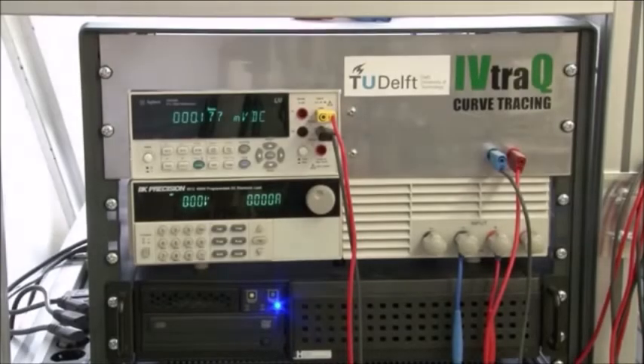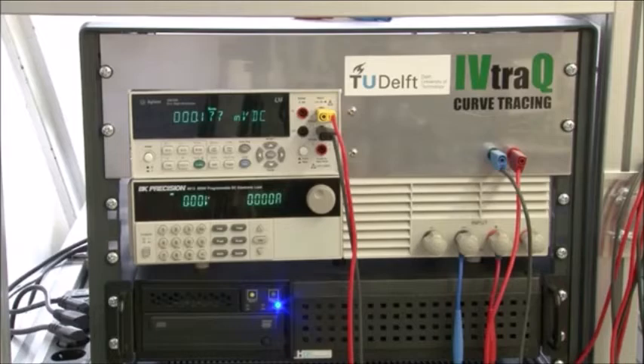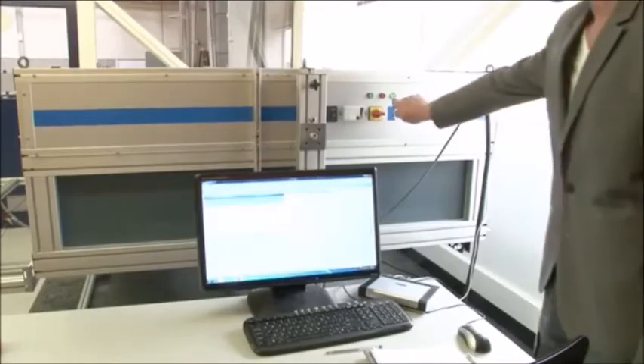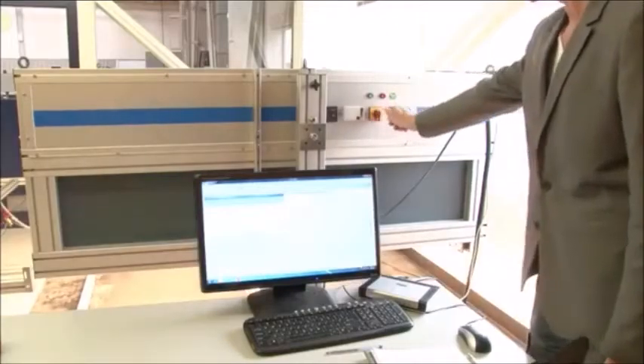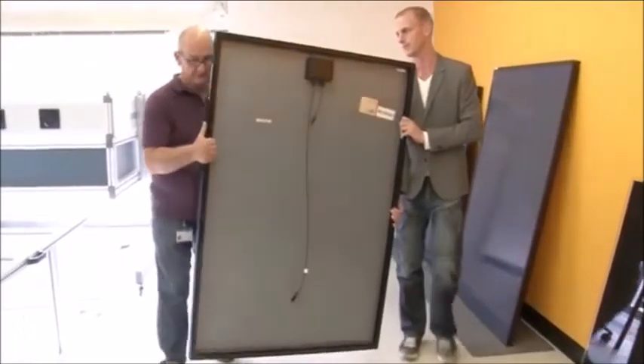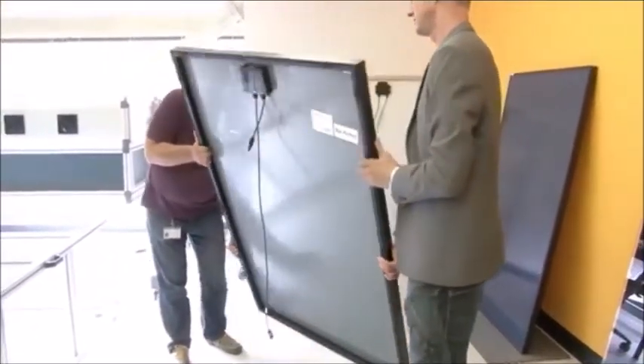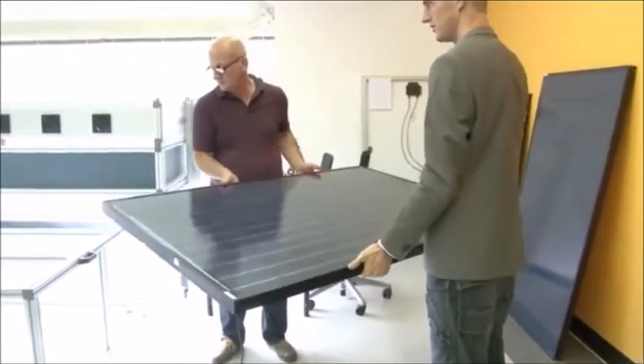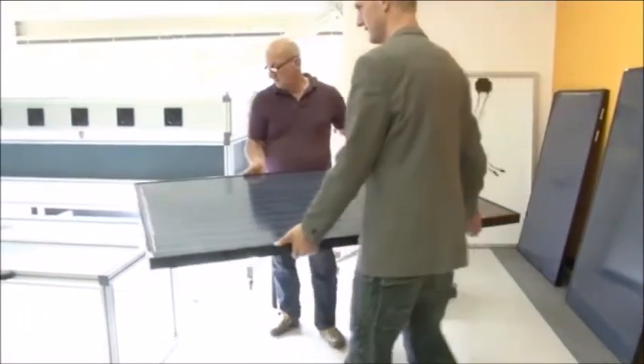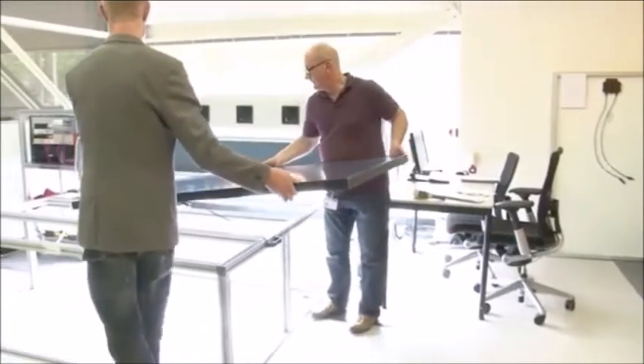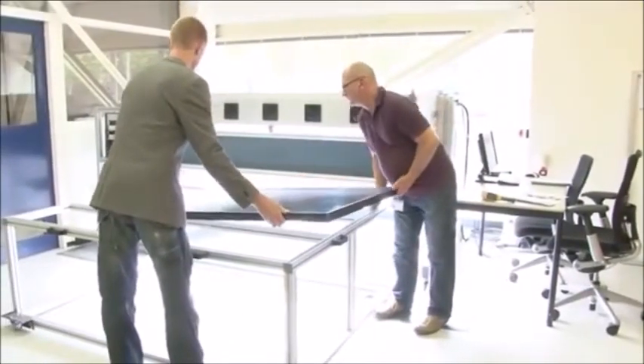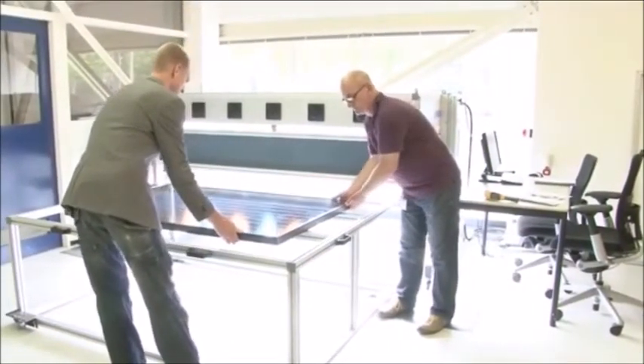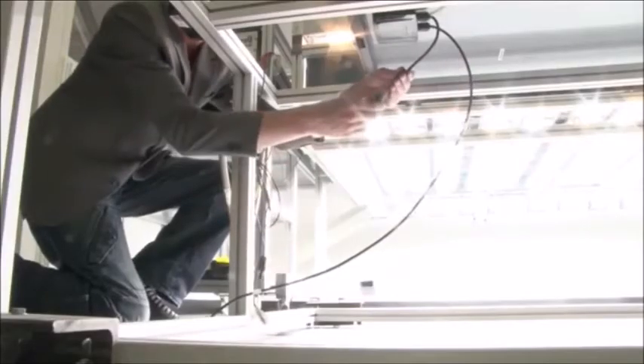Here you see the voltage supply and the ampere meter. Typical panel areas are in the range of 1.5 square meters. This means that you need a light source with a spectrum shape and irradiance which is homogeneously distributed over large areas. In the solar lab, we use a large AAA solar simulator from Eternal Sun. AAA indicates that the spectral match, the uniformity and the stability is of A-class quality.